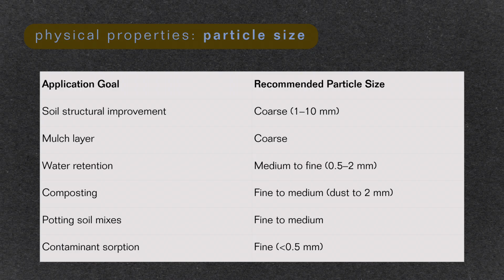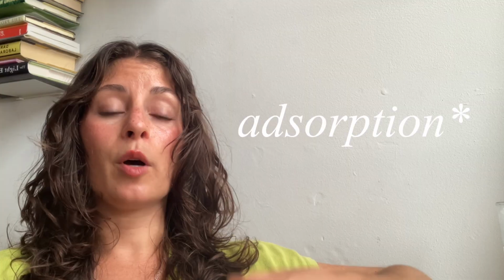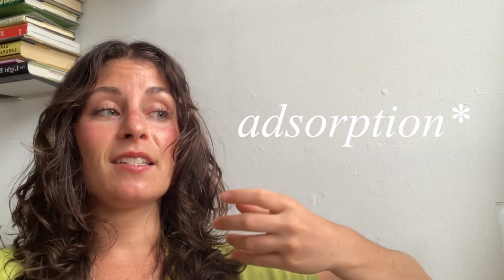because as that particle size decreases, the surface area of the particle increases. On the outside of the particle of the biochar, there are all these chemical reactions that are happening, adsorption and different things like that. So between the chemical and physical properties, to optimize for something like contaminant sorption, you want a more fine particle.